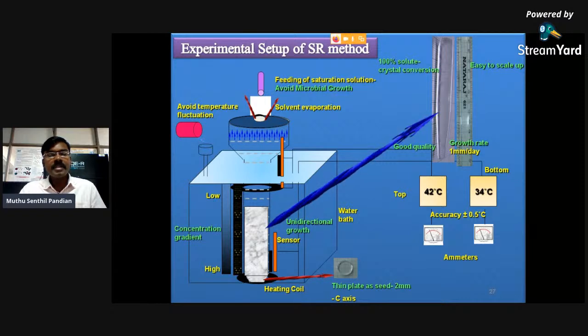After a few weeks or a few months, depending upon the solubility of the material, the crystal will be grown like this. This is the diglycine barium chloride single crystal grown by the SR method. From a thin plate like seed crystal, this large size crystal is possible in the SR method. Here we can optimize the growth temperature.